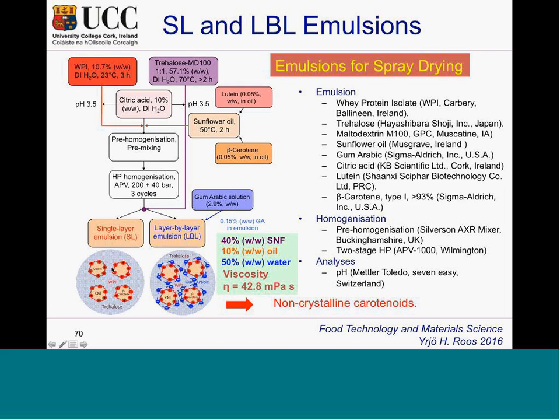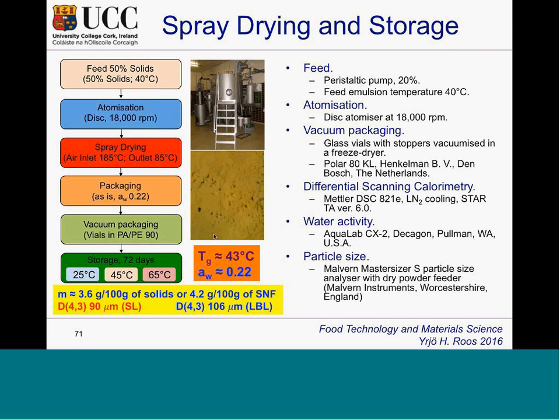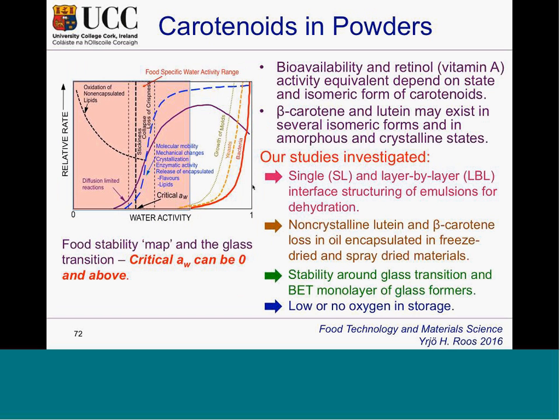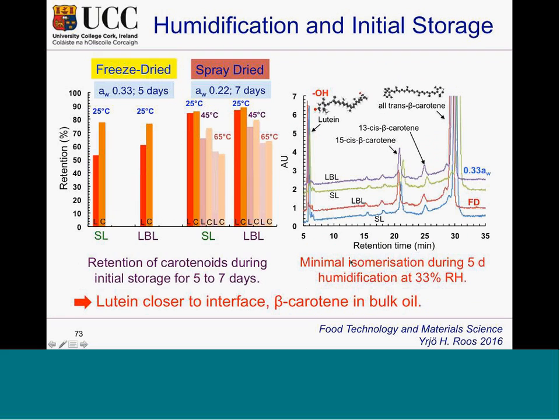When you make the powder, you have to have the glass former to make the structure that affects the oil and brings it to the solid stable state. And if we expose these to different humidities, you could study the properties affected by the glass transition, the structural changes, and so on. So we have investigated layer emulsions and the beta-carotene loss above and below the glass transition, and the stability. But it's somewhat complex in the carotenoid analysis, because you have isomerization and you want to get the different isomers. We have followed concentrations of all-trans beta-carotene and lutein in spray-dried and freeze-dried materials. So we have followed them in experiments.